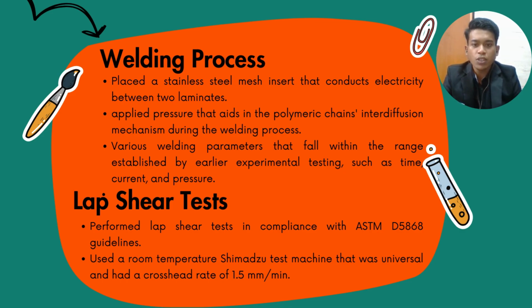Next, lap shear test. Perform a lap shear test in compliance with the ASTM D5868 guideline. Use a room temperature Shimadzu universal test machine with a crosshead rate of 1.5 mm per minute.